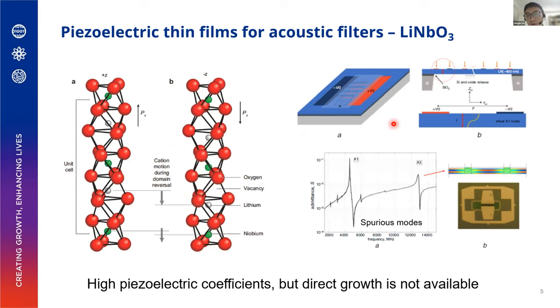The device performance, just now we were talking about the X-bar structure, has been very amazing. Performance for this X-bar structure has very high resonance frequencies. It's because the piezoelectric performance of lithium niobate is better than aluminum nitride. But the major problem for this material system is that direct growth of lithium niobate thin film is very challenging. And most of the devices demonstrated right now use this smart cut technology. So you transfer a thin layer from the bulk single crystal to the silicon wafers, and then you do these nano fabrications to get this device.